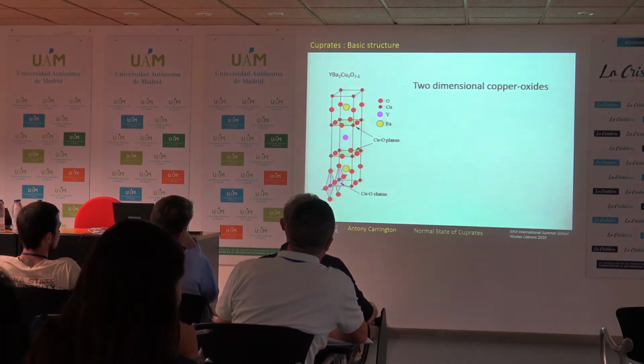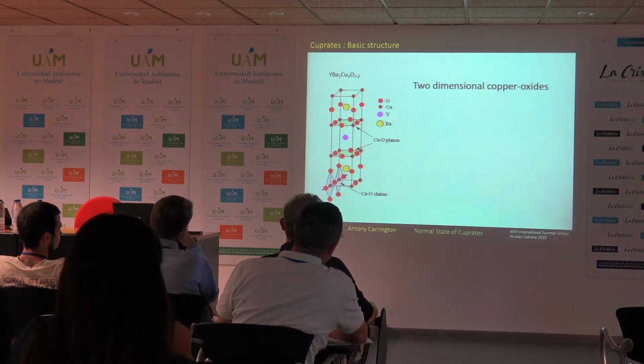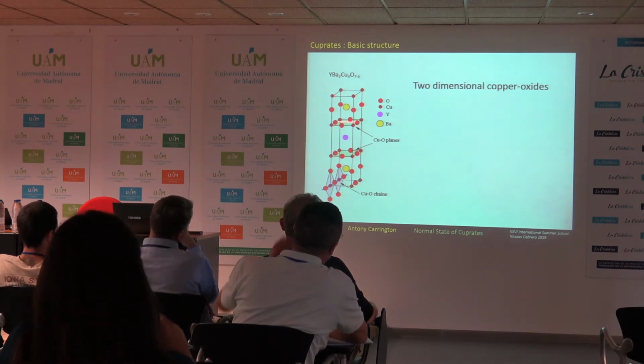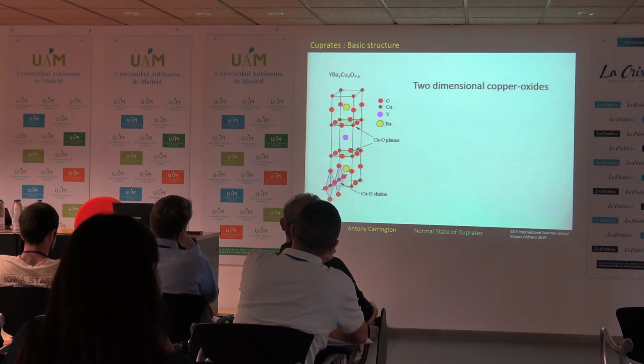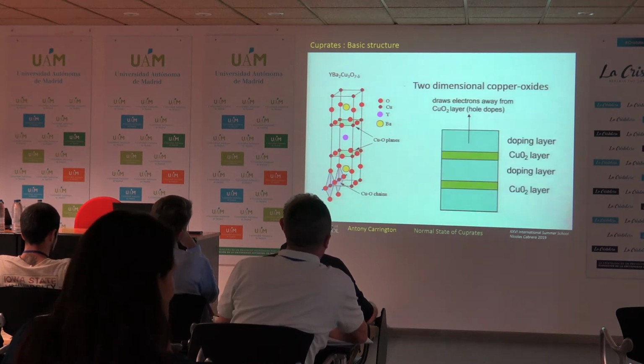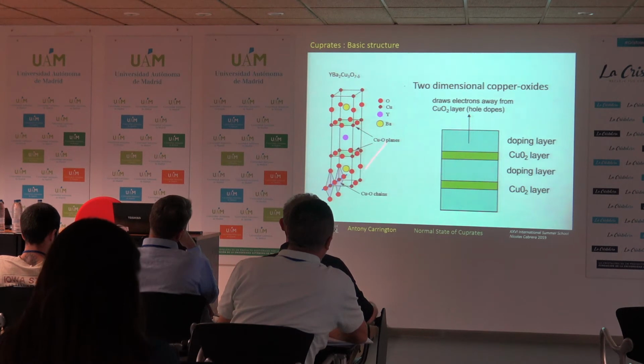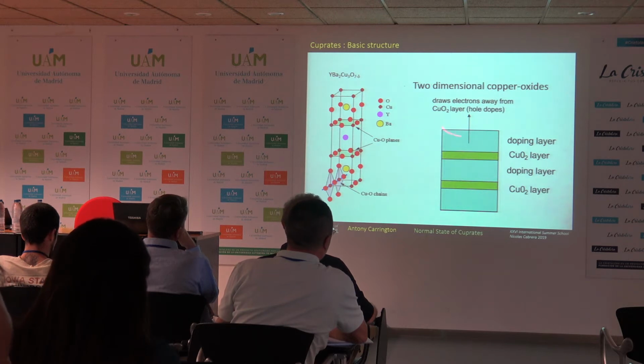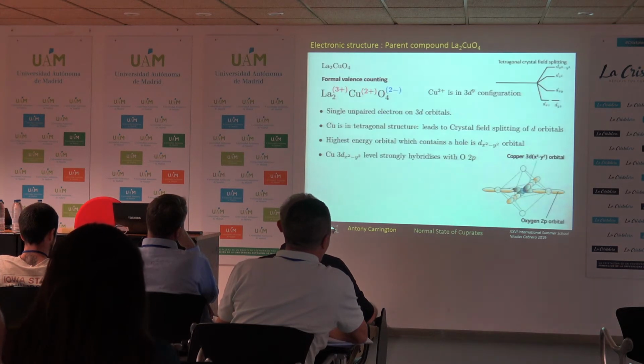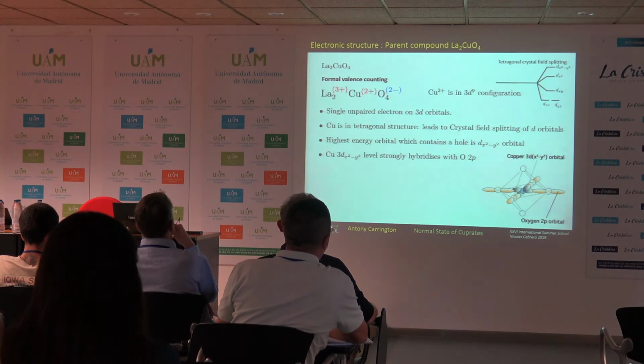Okay, so your basic structure of the cuprates is that we have these copper oxygen planes, and then we have a bunch of other stuff, and the bunch of other stuff basically pulls electrons away from these planes and ends up doping them. All of the cuprates have this in common, and as I said, in terms of whether they're clean or not, the main thing is how far away the disorder in the doping layer is from this copper-oxygen layer.